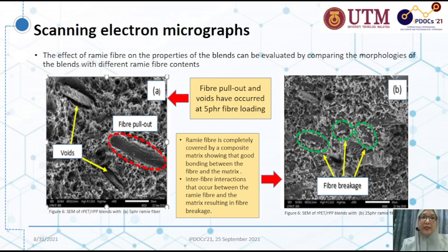Last one is the scanning electron micrograph. The effect of ramie fiber on the properties of the blends can be evaluated by comparing the morphologies of the blends with different ramie fiber contents. As we can see here from figure A, the fiber pull out and voids have occurred at 5 pHr of fiber loading, whereas in the 25 pHr of fiber loading, we can see there is some fiber breakage. The ramie fiber is completely covered by a composite matrix, showing that good bonding between the fiber and the matrix happened.